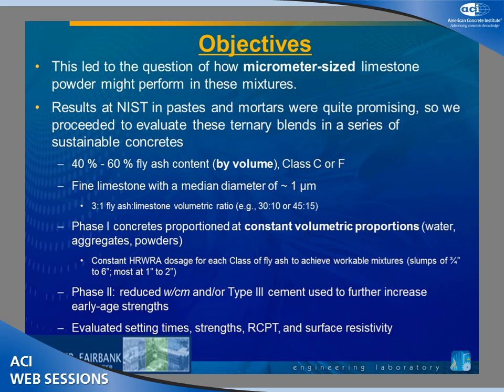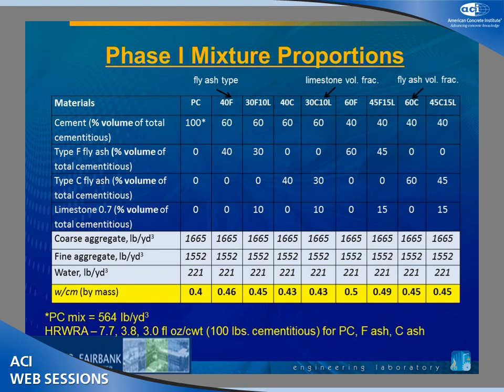We typically wanted to move our setting times by about 4 hours, so we were getting a 4-hour delay. The type 3 would bring us back maybe 1 or an hour and a half of that, so it wasn't sufficient in and of itself. We found the limestone to be much more effective, but certainly if we use limestone and type 3, they're both influencing the setting time. So what we looked at were setting time, strengths, rapid chloride permeability, and surface resistivity.